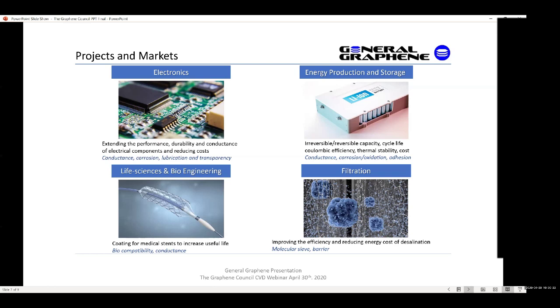For example, we are currently using these properties to develop desalination membranes that retard the rate of biofouling. And in another example, we have produced graphene polymer laminate composites with a tunable effective electronic conductance up to 10 Siemens per centimeter, and increased tensile strength and modulus of the polymer by up to 50%, depending on the number of graphene layers used. So you can see that graphene performance can be developed to tune to many different application challenges. The key here is finding a problem that's so important that it's worth solving with graphene.